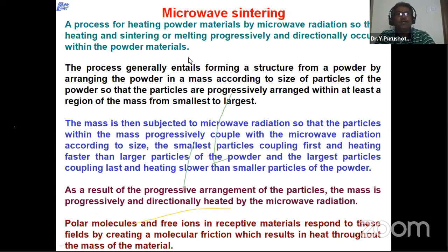Coming to microwave sintering, it is a process for heating powder materials by microwave radiation so that heating and sintering or melting progressively and directionally occurs within the powder materials. Here volumetric heating takes place in the microwaves, and the process generally entails forming a structure from a powder by arranging the powder in a mass according to particle size, so that the particles are progressively arranged within at least a region of the mass from smallest to largest.